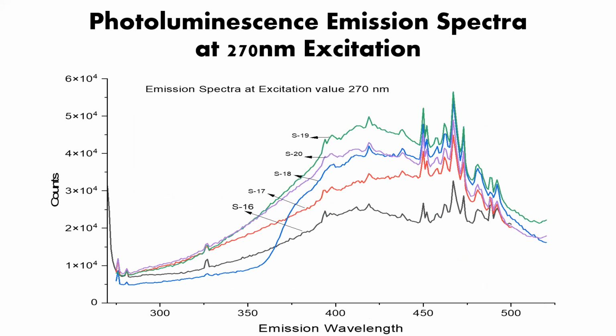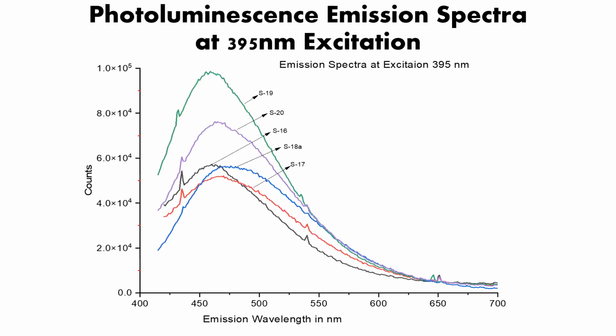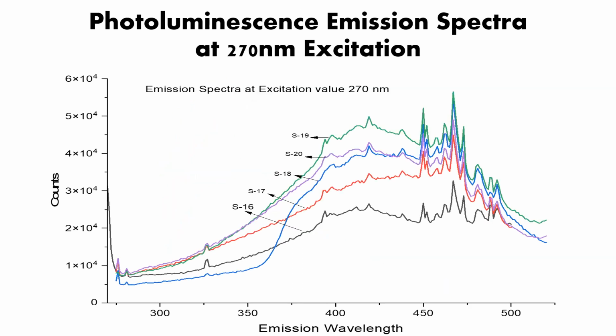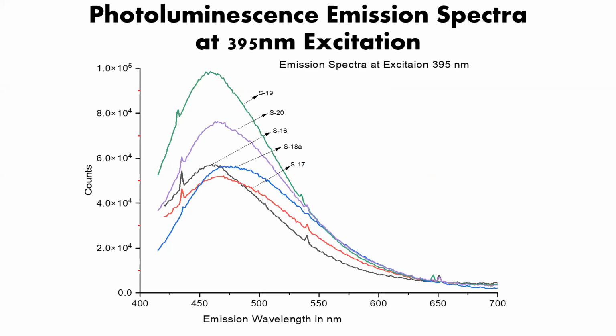I have excited under the UV region, and all the prepared samples showed different emission spectra. Again, I analyzed this tip-to-tip data. Tip-to-tip data means I found the peak-to-peak emission wavelength and counts. I again analyzed the basic fundamental mathematical modeling. Here I have two excitation values. One is a 270 nanometer excitation value, and in this case, I have a 395 nanometer excitation value. It means these two excitation values are under the UV region.